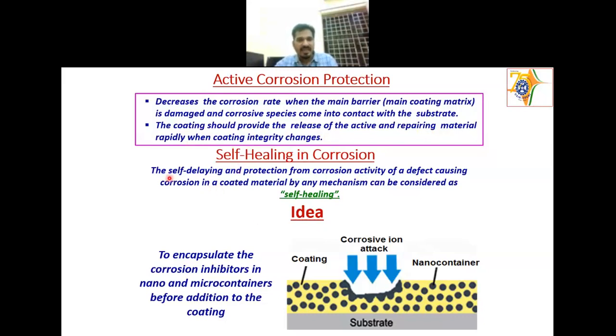So, how can you define self-healing in corrosion? We can say the self-delaying and protection from corrosion activity of a defect causing corrosion in a coated material by any mechanism can be considered as self-healing. That means if you see a coating here and you added some kind of nanocontainers here, and the nanocontainer may have some kind of stored inhibitor or some other chemicals. So when a corrosive ion attacks or a defect comes here and ions are coming in, the entry of the corrosive ion acts as a stimulus and the container breaks. With the stimulus, this inhibitor comes out, leaching is happening, a film is forming and stops further corrosion.